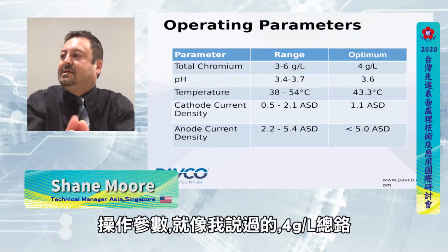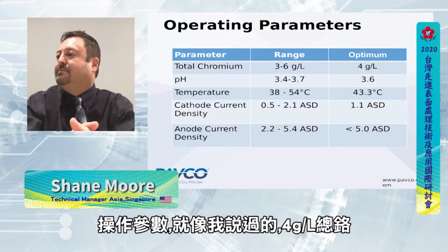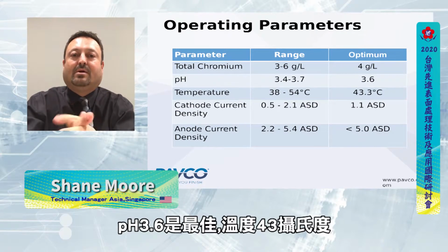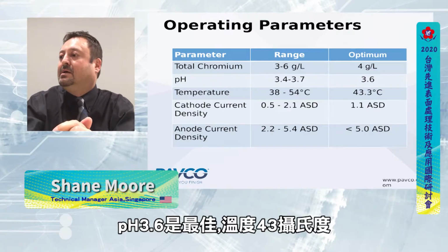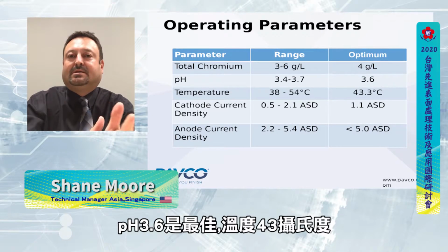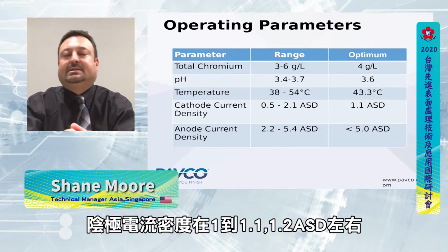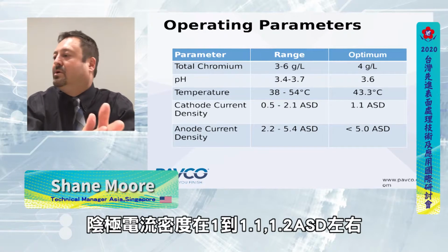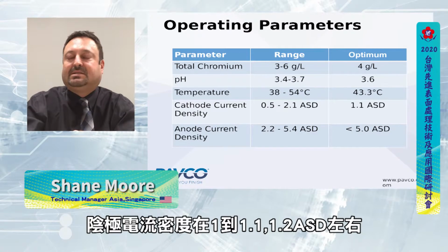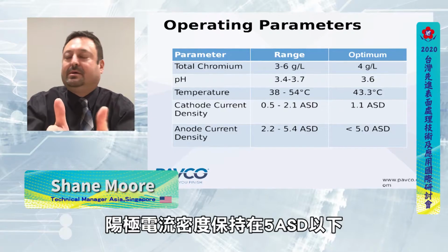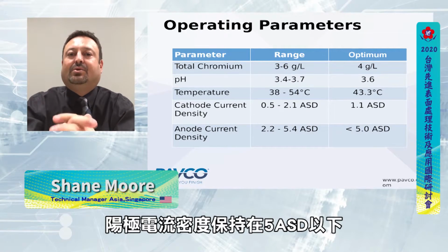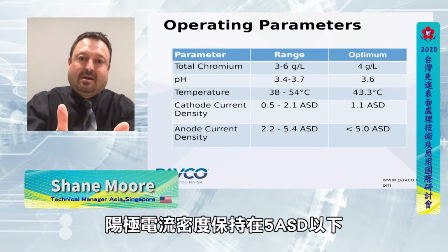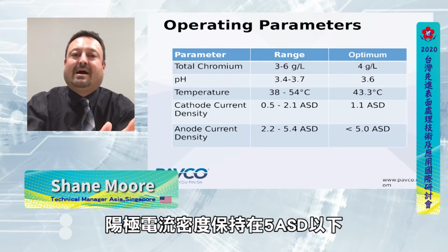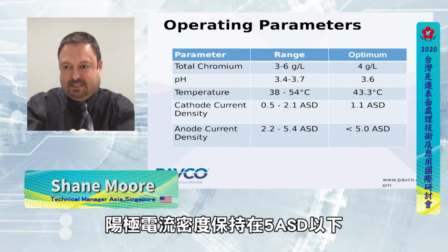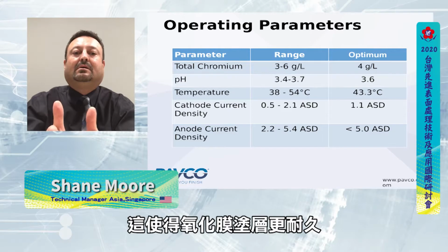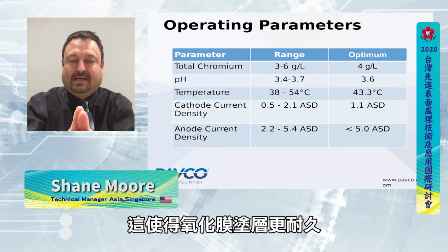Operating parameters, like I said: 4 grams per liter of total chrome. pH, we run around 3.6 as the optimum. Temperature, 43 degrees Celsius. Cathode current density, around 1 to 1.1, 1.2 ASD if possible. Whenever you're designing the tank, you want to make sure that the anodic current density stays below 5 amps per square decimeter, because that will allow the coating to last longer.